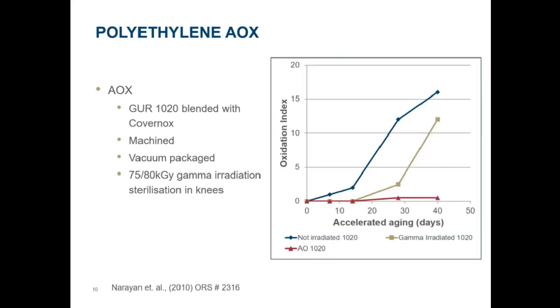On this graph, you can see how accelerated aging over time does affect the oxidation index for some polyethylene material. And you can see that the antioxidant polyethylene maintains its oxidation index at a low level, even under accelerated aging of up to 40 days, compared to gamma irradiated polyethylene or not irradiated polyethylene at all.